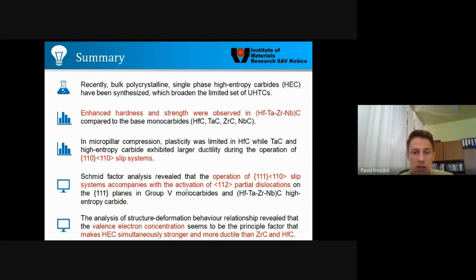Schmid factor calculation revealed that the 111 type slip system can be activated by partials, but this is only connected with specific crystallographic orientation. So in case of indentation, it's possible, but in case of micropillar compression, it may not be possible. And the structure deformation behavior analysis revealed that valence electron concentration plays a significant role in deformability, and this may make high entropy carbides stronger compared to zirconium or hafnium carbides, and more ductile at the same time.